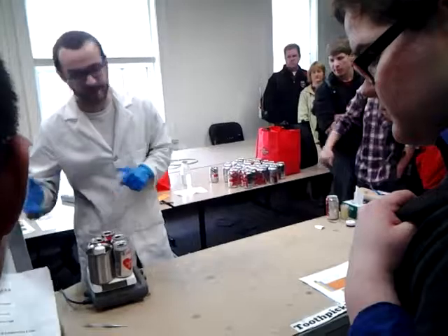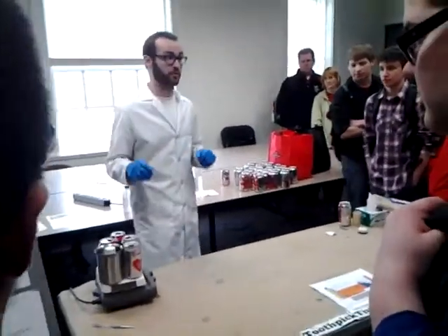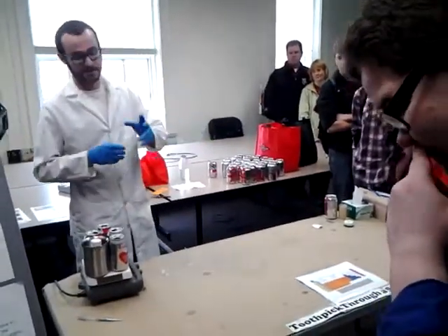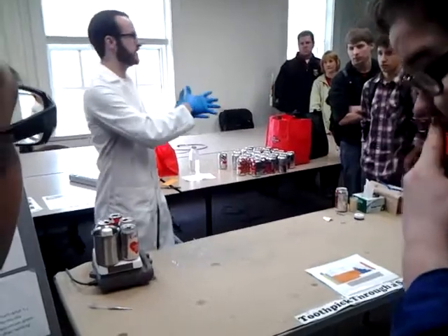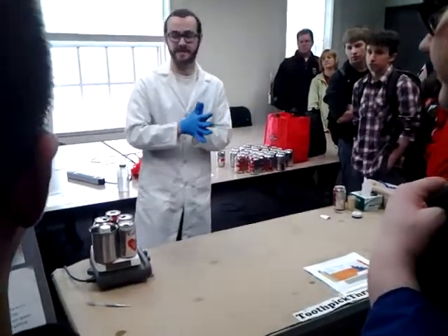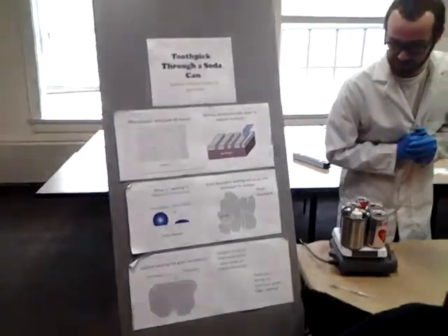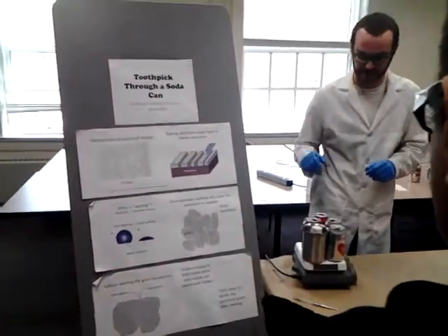On the other hand, gallium, liquid gallium, and aluminum really like to be near each other. So gallium is going to find as much surface area of the aluminum as possible to be in contact with. So it's going to penetrate through all these grains, all these grain boundaries, and be in contact with as much aluminum as it can be. And that weakens the structure of the aluminum.